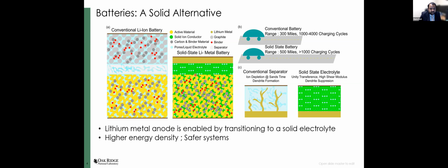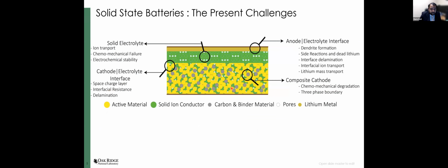You replace a liquid electrolyte with a solid counterpart, and then you replace that porous anode, which is graphite in the conventional lithium-ion battery, with metallic lithium. Now, however, with these systems, there are lots of issues, and the issues are cascading at multiple scales. At all the components of the solid state battery, we are facing challenges. In the composite cathodes, we have chemomechanical degradation and three-phase boundaries. We have space charge layers and reactions at the interface of the cathode and the electrolyte. The electrolyte itself undergoes fractures and filament formation, and the lithium metal anode is unstable as well.